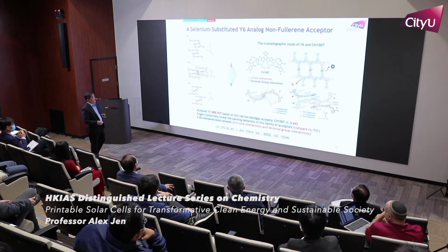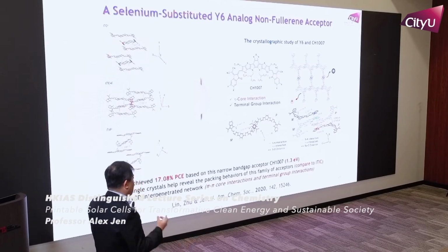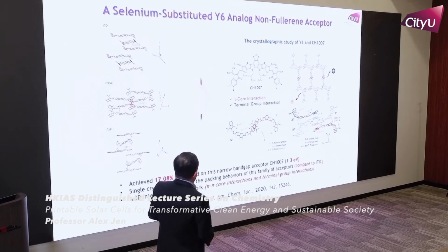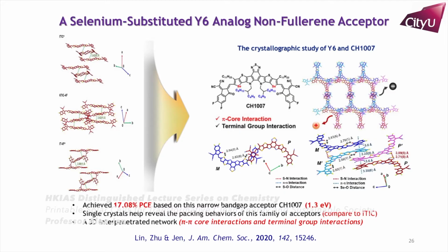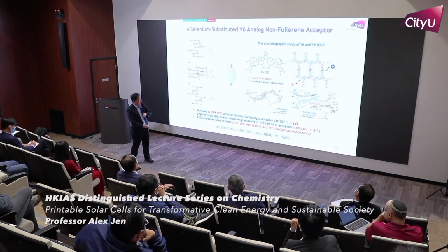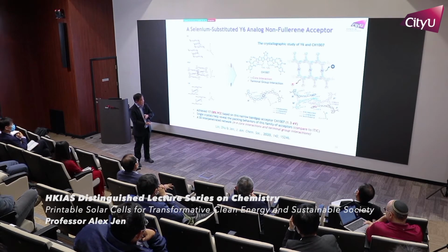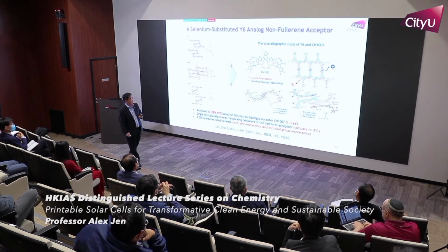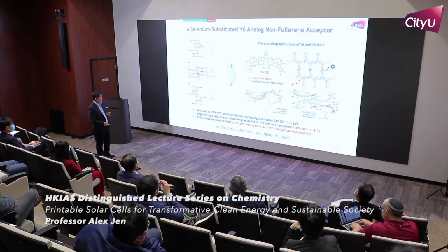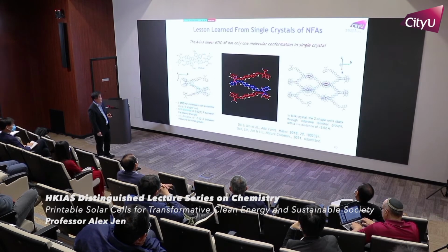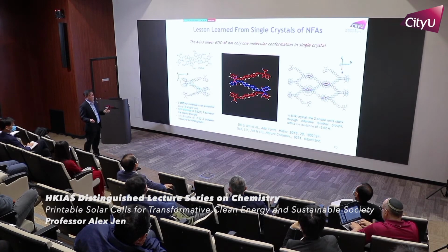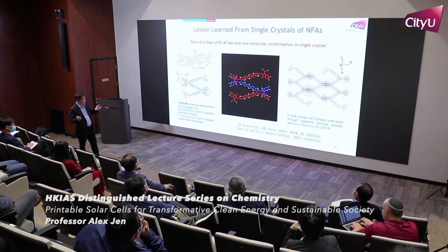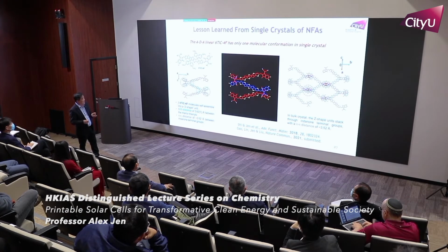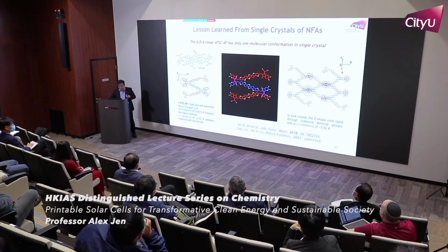More recently, our group, by tuning the heteroatom, instead of sulfur, put in the more polarizable selenium onto this molecule, and then you can see, because of the stronger selenium interaction, it really helped the packing in a tighter space. So your pi stacking and those acceptor interactions, if you look at their crystal structure, form tighter packing. As a result, you can go to 17% power conversion efficiency. And I will show you some of the things we learned, because we have an expert here to do all kinds of molecular simulation and molecular dynamics, but also how we, as material scientists, can learn from the fundamentals. This is a single crystal grown from that.